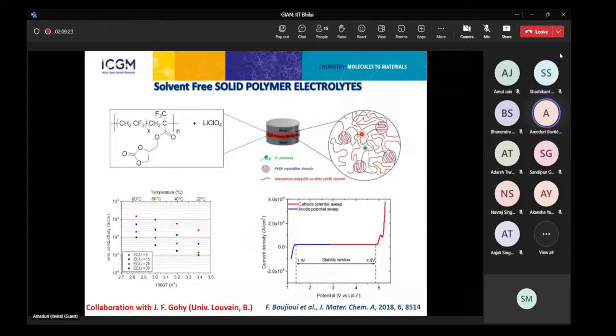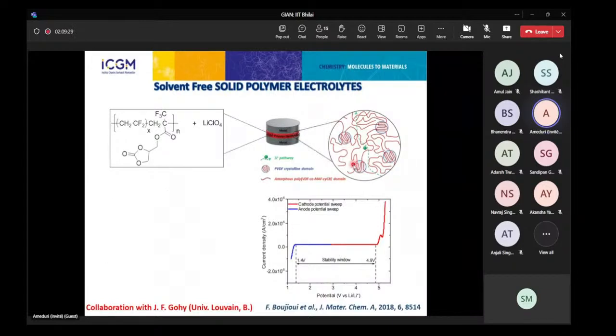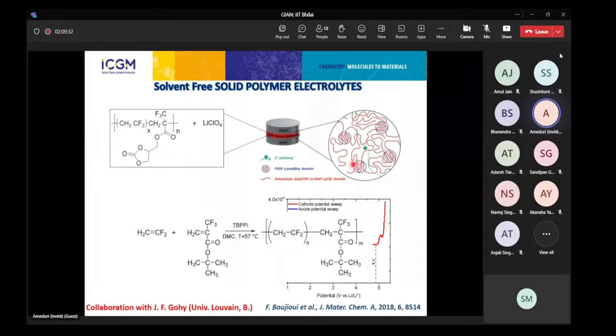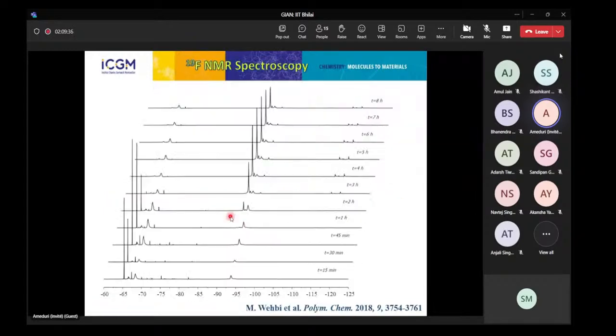And we wanted to understand what's going on here. So we said, okay, maybe we can design a specific reaction in which we could understand what's happening. So we made a kinetics of radical copolymerization. And in this way, along the time, we measured the NMR spectrum. So, you know, we like NMR a lot. And we could see that a first unit based on an alternating copolymer between MAF cyclocarbonate and VDF was prepared. So this is the unreacted MAF, which after 30 minutes is decreasing, and then this is stopping. And this stops more or less concomitant to another signal which appears, which is linked to the presence of PVDF.